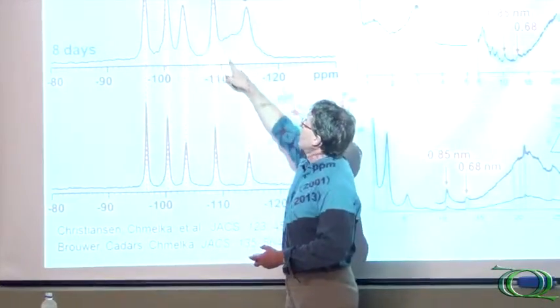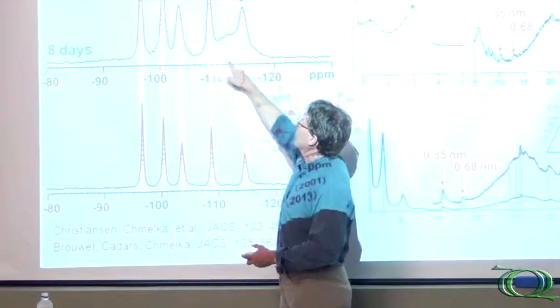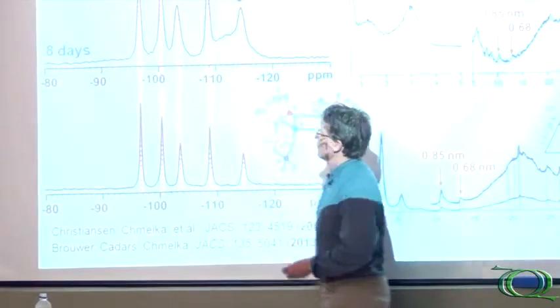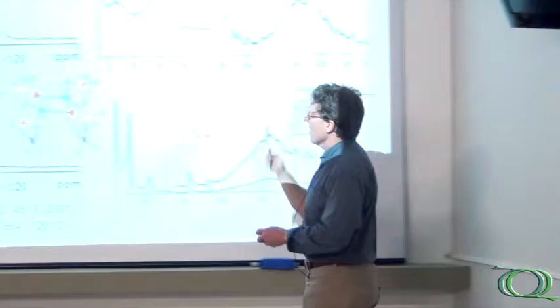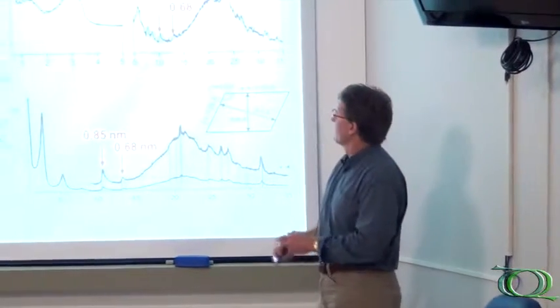We also see those out here, but these are from some of the crystallization has gone further to start forming ZSM5. But we have the layered silicate materials here which are due to the five peaks you see here. And in fact, this higher reflections here is due to the fact that this is the representation of the crystallization of ZSM5. So it's partly continuing. We haven't stopped it at only the layered silicate. It's a mixture of structures.